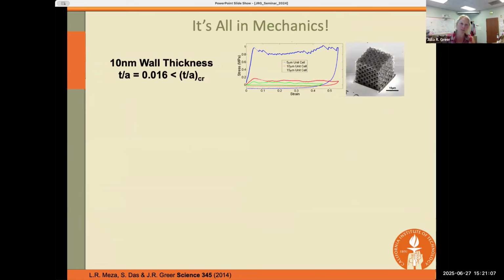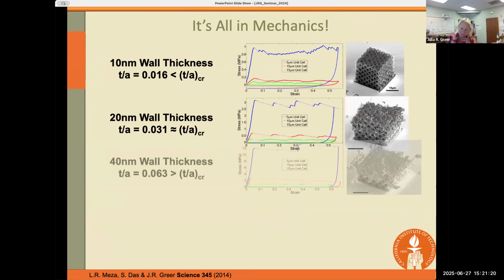So let's see what we're observing. For the 10 nanometer wall thick materials, this ratio is 0.016, so it's below 0.03. You can see that every sample recovered, and the different colors represent different sizes of the unit cell.